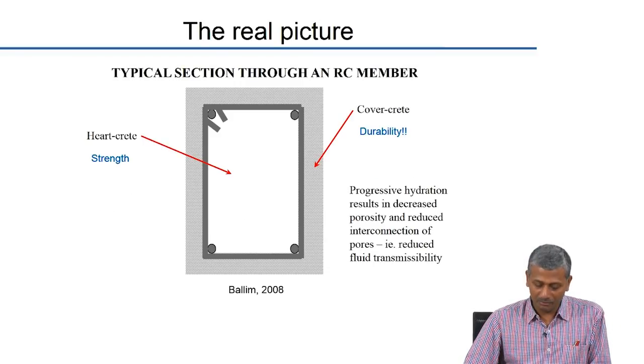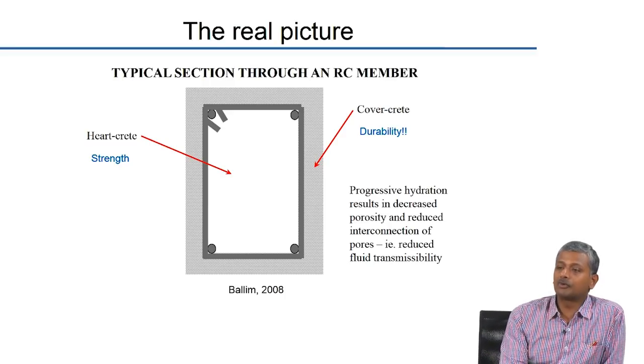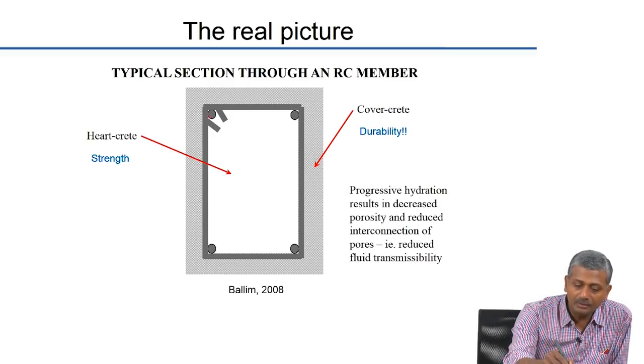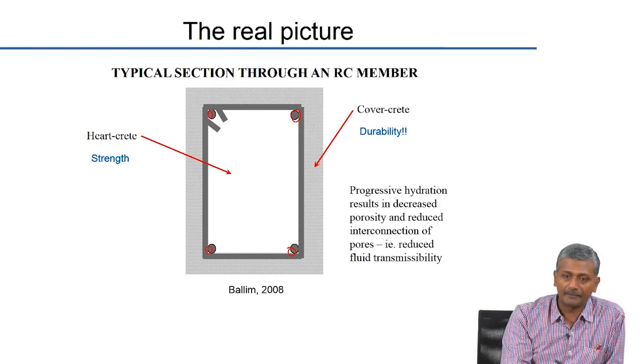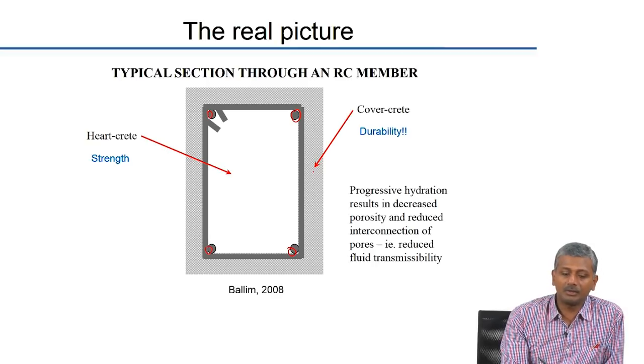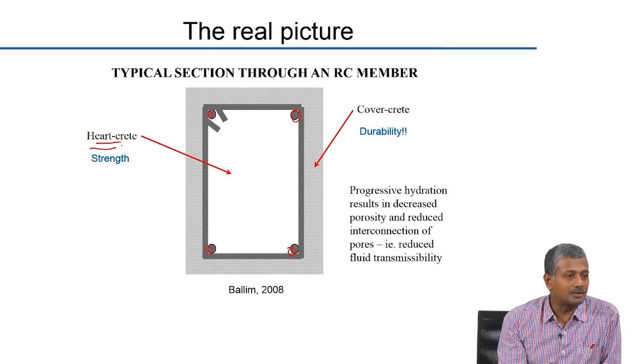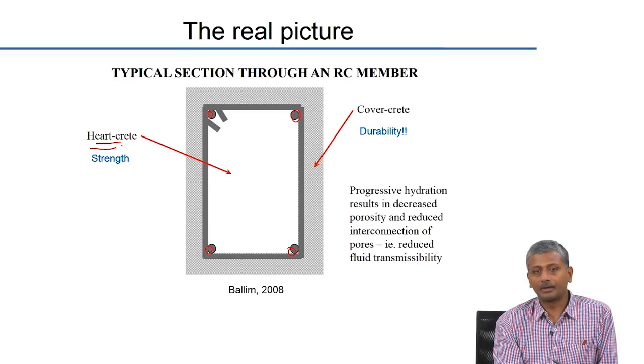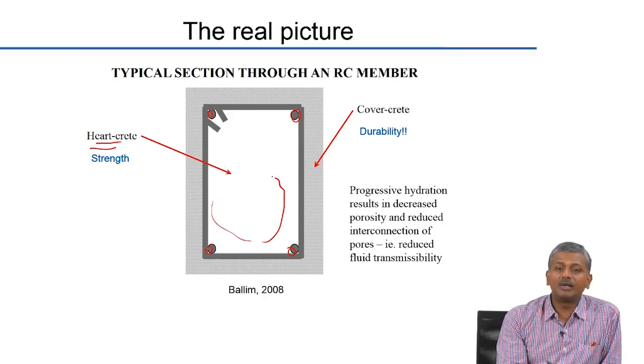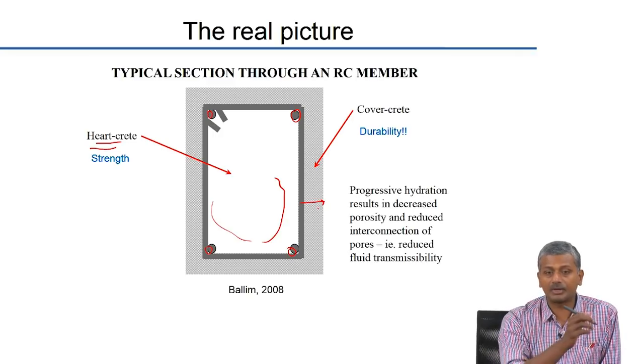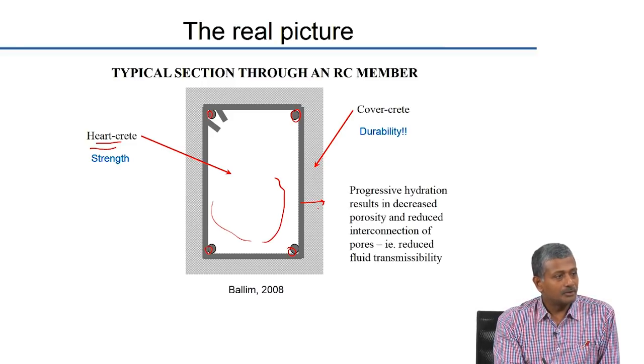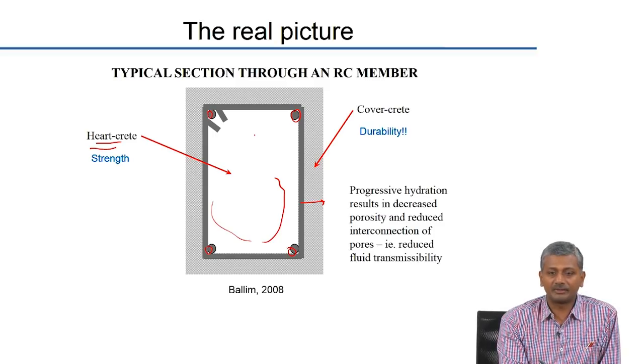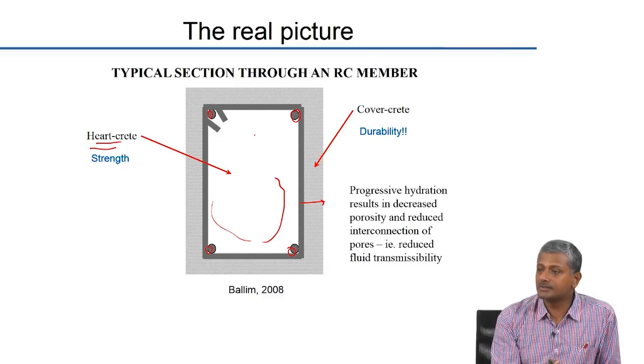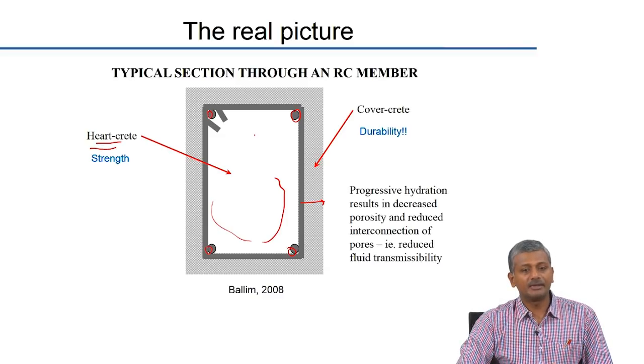There are a lot of problems that you can expect in concrete, for example, if you don't do curing. So let's take an example of a typical reinforced concrete member, like a concrete column, right? You have steel, which is the primary longitudinal steel, and you have the tie bars around the steel, okay? The concrete that sits outside the steel is called the cover concrete, whereas the concrete sitting inside can be called the heart-crete, okay? That's a common terminology that people who deal with durability use. Now, if you don't do any curing for this column, it's very difficult to imagine that the water sitting inside will ever be able to dry out of the concrete, because it has to travel a large distance to come out. So if you don't do curing in this system, the concrete sitting inside the steel is not going to be affected much by that. That means your strength development will gradually happen at the right level that you want. In other words, lack of curing in a column may not compromise the strength of the column.